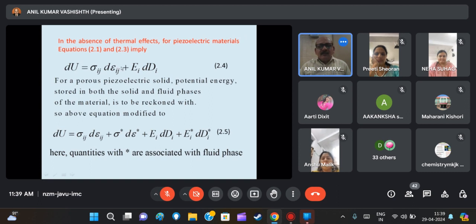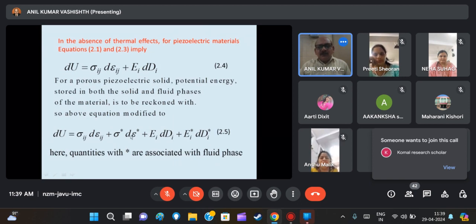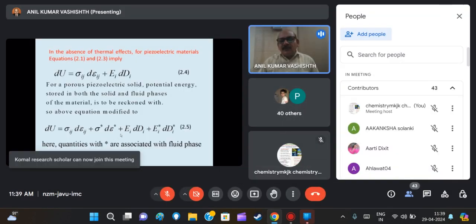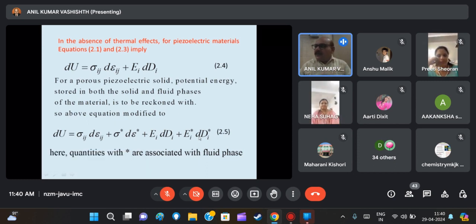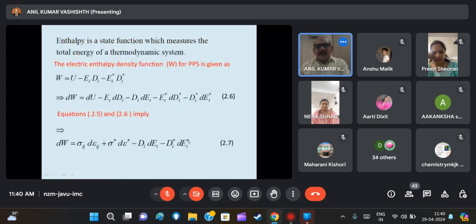We applied this equation and accordingly modified the strain energy, which is equal to sigma ij d epsilon ij and sigma star d epsilon star. The star corresponds to the fluid phase, so this term is added into the strain energy expression due to the liquid phase. Similarly, Ei star dDi star, which comes from the work done by the electric forces with the electric displacement Di star in the fluid phase of the material. So this equation was modified like this.